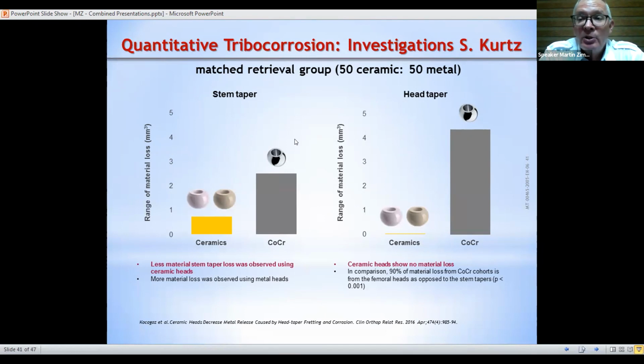Knowing that ceramic is much harder than cobalt chrome ball heads, we could expect more damage on the taper, which is not the case. So it is effectively not only a problem of mechanics or friction between two surfaces, but also a chemical reaction. That's the reason we call it fretting corrosion reaction. So we have less damage on the stem taper.